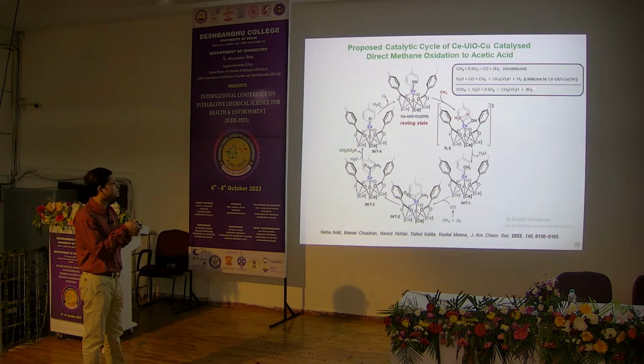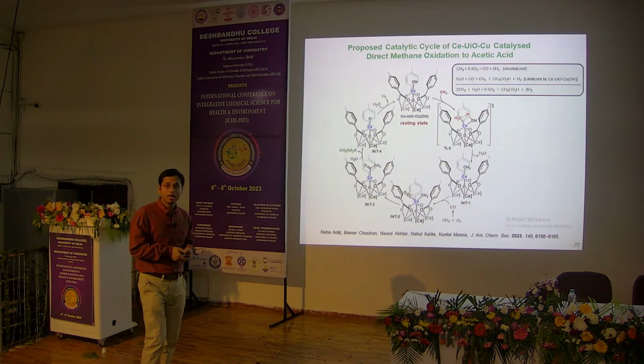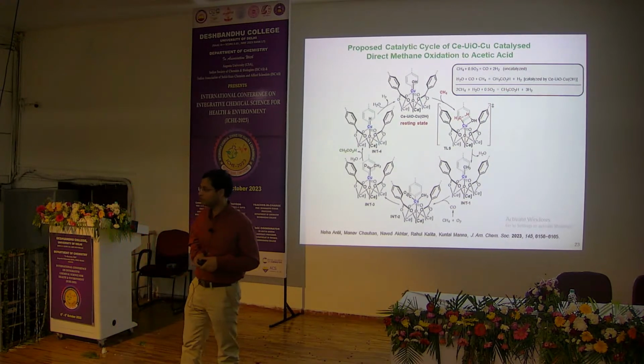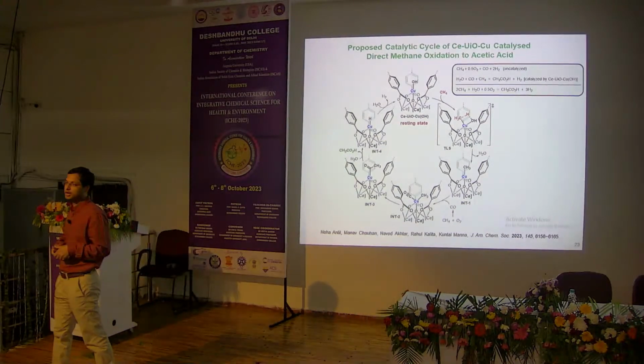That CO is coordinated to the copper to give this species, and then the insertion of the CO with the copper methyl species gives this intermediate 3, and then hydrolysis with water gives the copper hydride and acetic acid product, and then hydride reacts with water to give the copper hydroxyl species. And this is the balanced chemical equation. The 2 methane molecules with 1 molecule of water and half molecule of oxygen give acetic acid, and hydrogen,